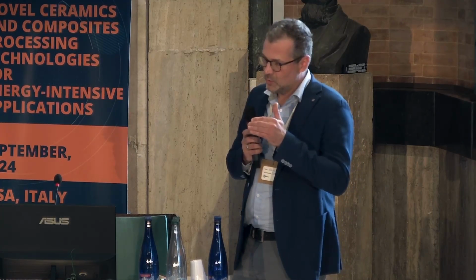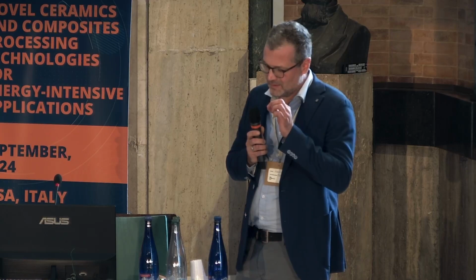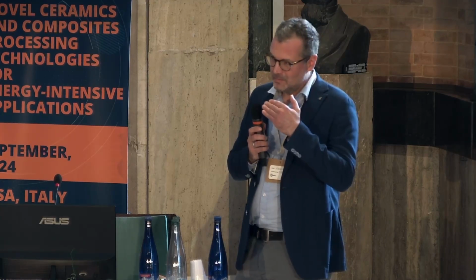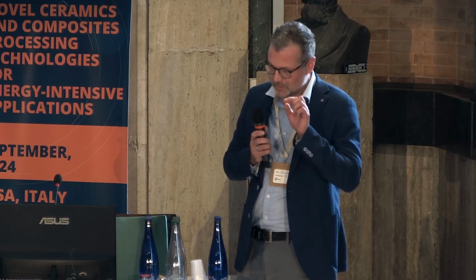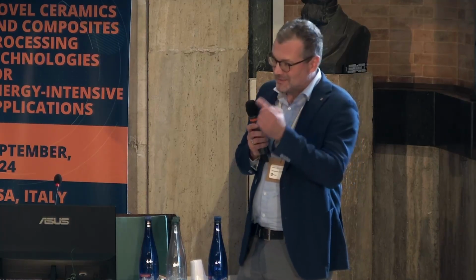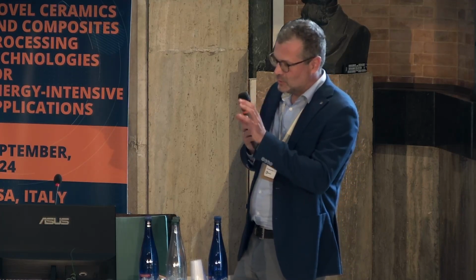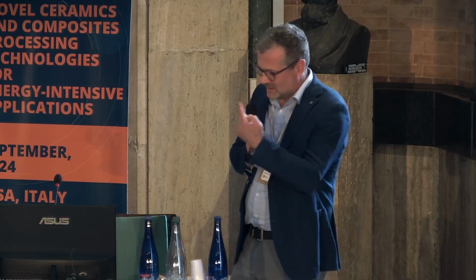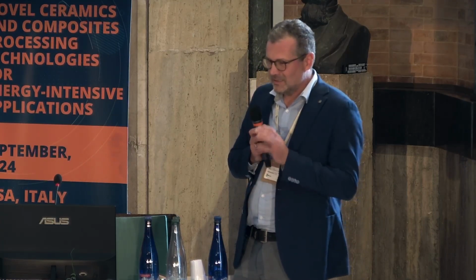And the reason why we did not use thermography is that some defects in the inner parts will not really be visible in high resolution, because sometimes the defects are smaller than the distance to the surface of the tube. So we can do it, but the round tube is not so easy, because with a round tube in thermography you should somehow rotate your sample, and it's not so easy. Planar it's okay, but we have some problems to unroll the whole thing for the thermography. So the CT is always the way we do it.